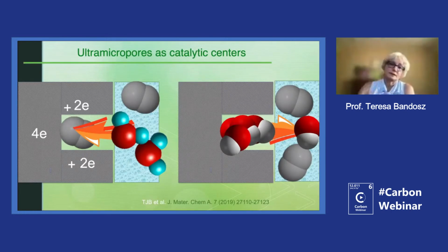So this is our first scenario, what we think happens in ultramicropores. And once again, we think about the pores which are small in size, similar in size to the oxygen molecule. So oxygen molecules are in water, then those pores are hydrophobic, so they withdraw oxygen from the electrolyte. And since water is very close, we have the strong adsorption potential, we have the splitting of the bonds, we have formation of OH, and that OH doesn't like to be in these pores, it prefers to go to water. So the site is open for another oxygen reduction in the pseudo-catalytic process.